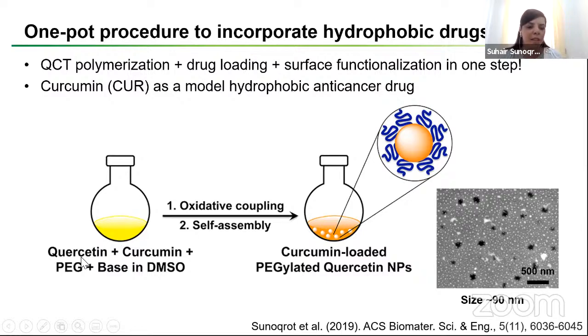So we incubate the quercetin with the model hydrophobic drug we used, which was curcumin, and the polyethylene glycol plus a base like triethylamine or pyridine in DMSO, a water miscible universal organic solvent. So we hypothesized that if we mix them together, the base will oxidize quercetin and it will be able to form a polymeric structure.